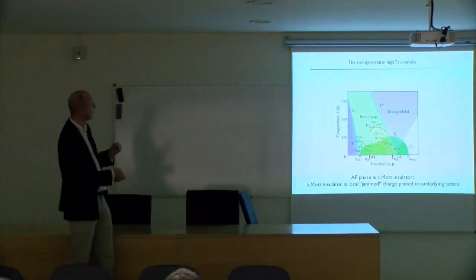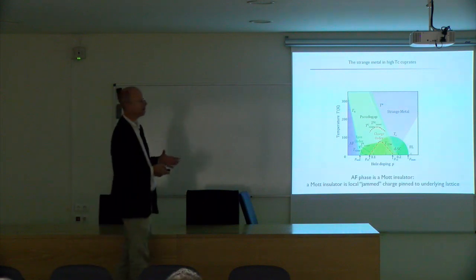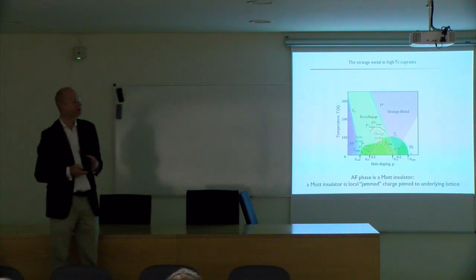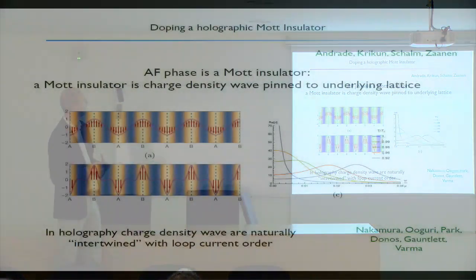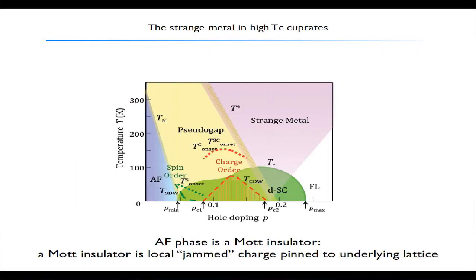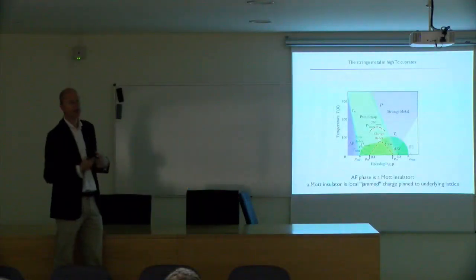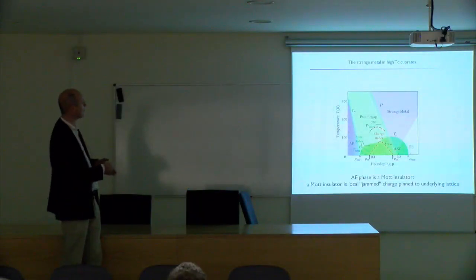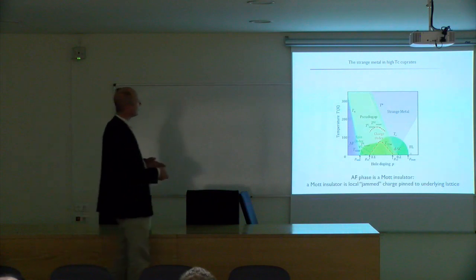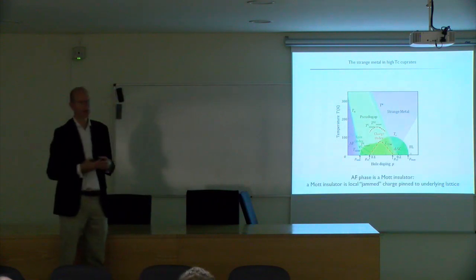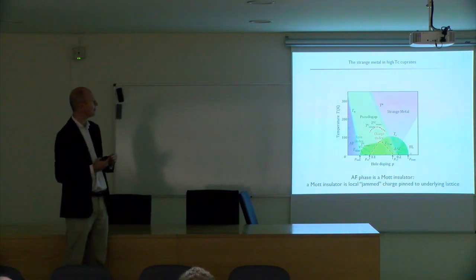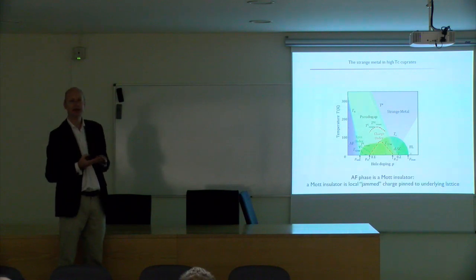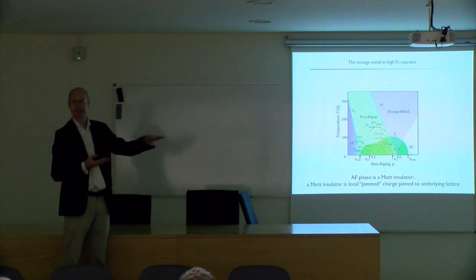Remember, this is the onset of superconductivity, but we're now going to go a little bit to this underdoped area where you have something called a pseudogap and a charge ordered state. I'm not going to go into too much detail, but the important part is that at zero doping, all these high Tc superconductors are actually insulators. They are a funny insulator called a Mott insulator, which is really locally jammed charge pinned to the underlying lattice.